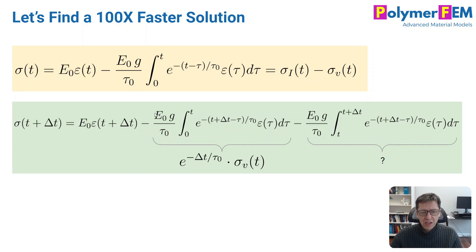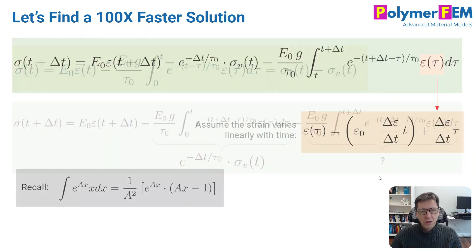If you look at this equation carefully, you can actually see that it becomes almost the same as this one. It's an exponential function of minus delta t over tau zero times the viscous stress that you have in the previous increment. So if you keep track of that, you can calculate this whole integral very quickly, because you just have to multiply it by this viscous dissipation of whatever stress you had in the previous increment. That's really cool. We still have another integral here that we haven't figured out what to do with, but this is a much easier integral to calculate in some sense, because it goes only from t to t plus delta t. It's a short time interval integral, and we can do some other tricks to solve this numerically efficiently.